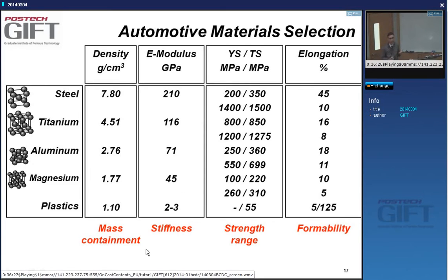stiffness is important for structures. Strength is important. And then if you want to make something out of them, formability of a material is also important. If you look at, for instance, the modulus to have an idea of the stiffness, steel has a modulus of typically 210. Titanium is already half that amount. Aluminum, a third of that amount, magnesium, a fifth, and plastics have no stiffness whatsoever. So if you want to make something stiff out of magnesium, it will have to be more voluminous, right? So the advantage of having a lower density is not really 100%, because you need to use more. In other words, your part will have to have a larger cross section